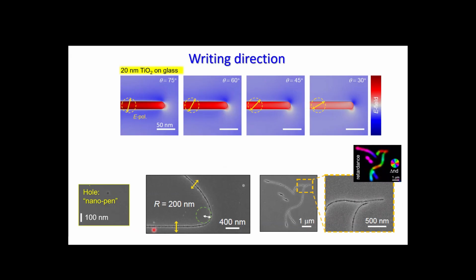Experimental results show that up to a curvature with a radius of 200 nanometers, you can just steer and ablate the nano groove. What is also interesting is that you can write two lines quite closely, which is absolutely unique for this type of patterning.